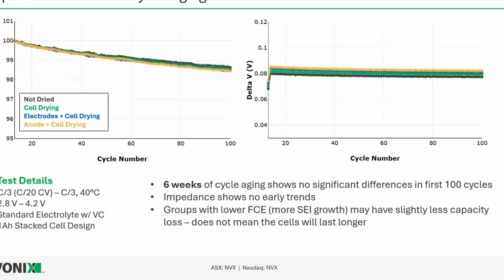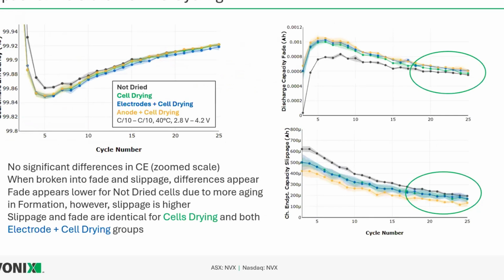So again, this is standard cycling, C/3, C/3 on a normal cycler. While this is going on, we threw everything on UHPC. And this is where we can start to do what we did with the cathode study and split up CE and fade slippage, see what differences we find. So here we've got Coulombic efficiency, and we can see there's almost no difference between any of these groups in Coulombic efficiency. And again, this is a very expanded scale, 99.8 to 99.94. So there's very little difference here, and especially the variation between the groups, there's no difference in CE.